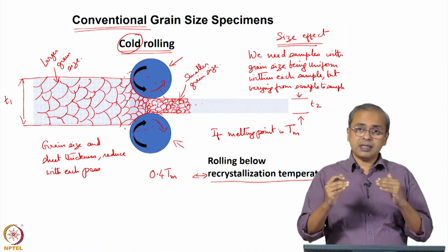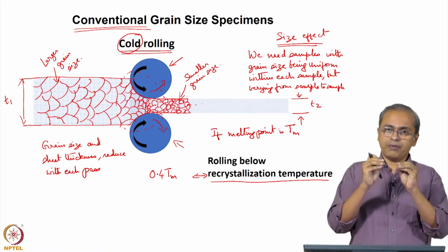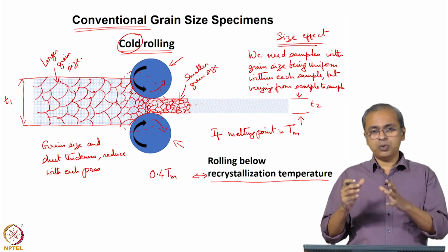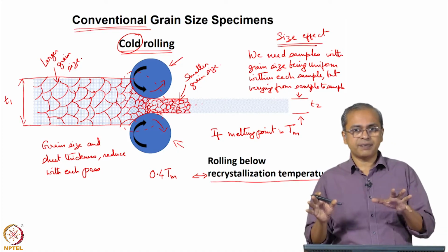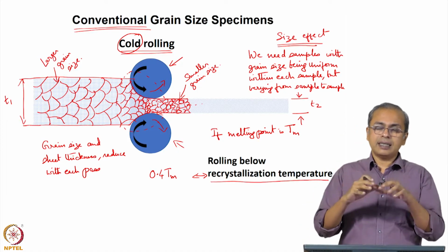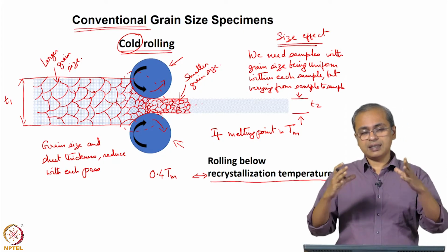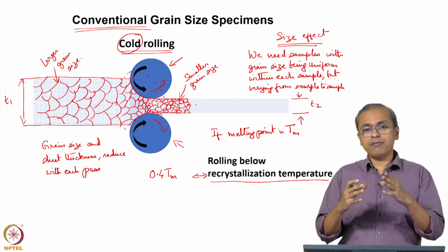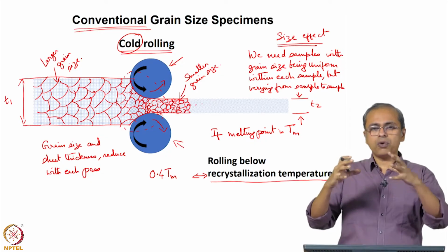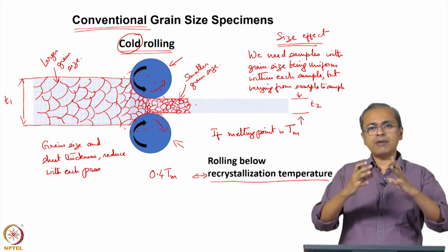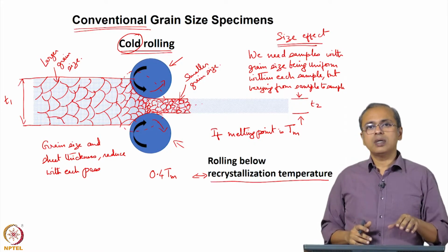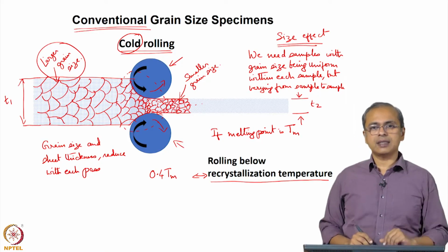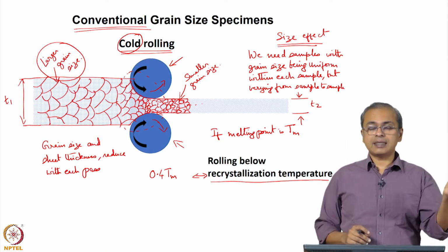What happens is if you cross this temperature, the small crystals that you have created actually have higher energy because you have created more grain boundaries, and as you know, grain boundaries have bonds that are not satisfied. So, if you have more grain boundaries, that is a higher energy state relative to crystal sizes which are large, which therefore have fewer grain boundaries compared to the volume. If you take it to high enough temperature, 3-4 of the smaller grains will coalesce, come together and form one larger grain. So, you will go back to the kind of grain structure that you have here. If you go to higher and higher temperatures, you will keep getting this grain structure. The sheet may be thin, but the grain structure will be large.